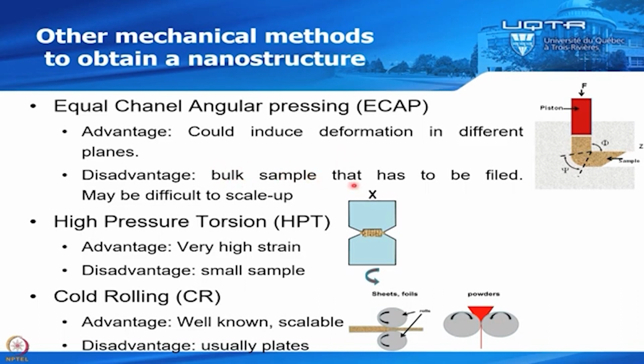The disadvantage is that the bulk sample has to be filed. So after you process that, typically this dimension is maybe 1 centimeter. So you have a block of 1 centimeter by 1 centimeter by maybe a couple of centimeter long. And you have to file this block. So you more or less modify your sample by doing that. You induce some other deformation by just filing or by reducing in powder. And also this could be difficult to scale up.